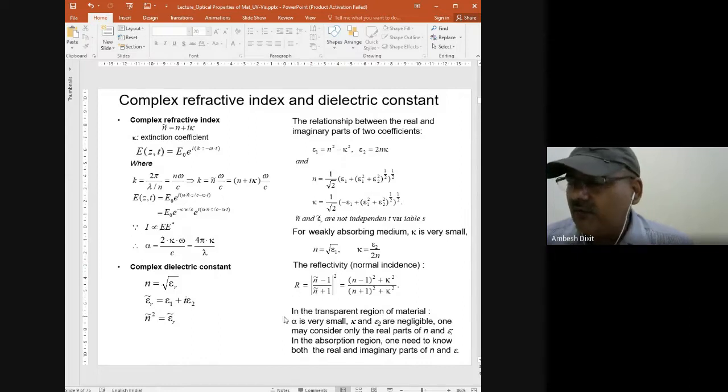I measured alpha, then computed k as a function of lambda, so I don't need to do fitting on the k side. I only need to do fitting on the n side, so 50% of the complexity is reduced. Earlier it was a two variable process, and now I have only a one variable process, which is much easier to work out mathematically when fitting.